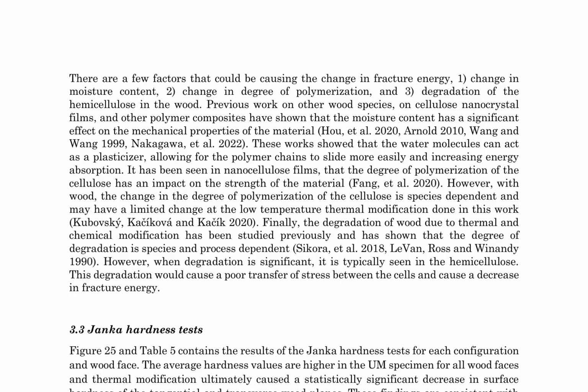The observed change in fracture energy of Western hemlock wood specimens can be attributed to several factors, including changes in moisture content, degree of polymerization, and degradation of hemicellulose. Previous research on various wood species, cellulose nanocrystal films, and polymer composites has demonstrated that moisture content significantly affects mechanical properties, with water molecules acting as a plasticizer to increase energy absorption. The degree of polymerization of cellulose has been shown to impact the strength of nanocellulose films, although this effect may be limited in wood due to species-dependent changes in degree of polymerization at low temperatures.